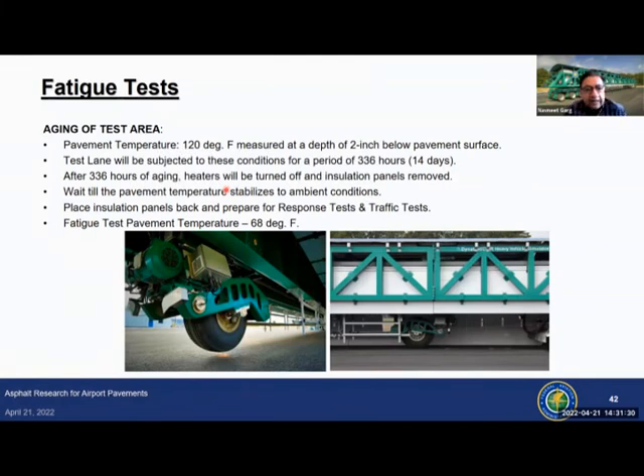So for fatigue tests, we decided to age our pavement test sections before starting tests. So we are aging these sections at 120 degrees Fahrenheit, measured at 2 inch depth below pavement surface. And we position HVS over the test lane, turn on the heaters to 120 degrees, and we let the HVS sit there for 14 days. So that's about 336 hours of aging at this temperature. And after 14 days, we turn off the heater, remove the insulation panels, and let the pavement temperature stabilize to ambient temperature conditions. And then we put our insulation panels back and start fatigue tests.